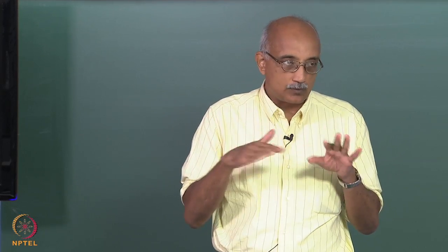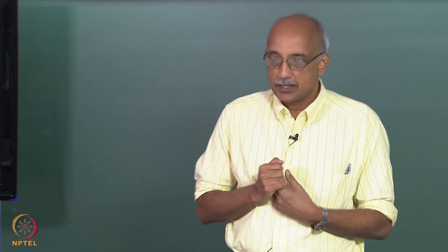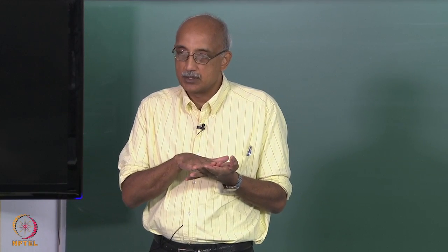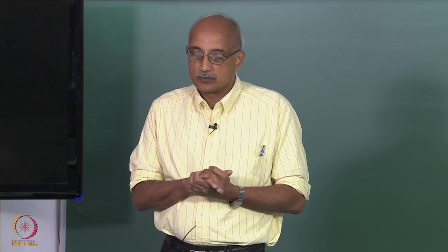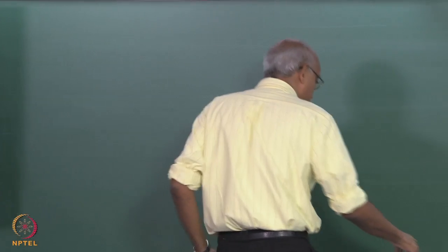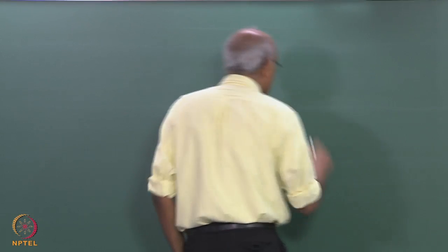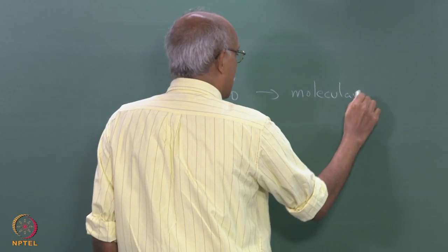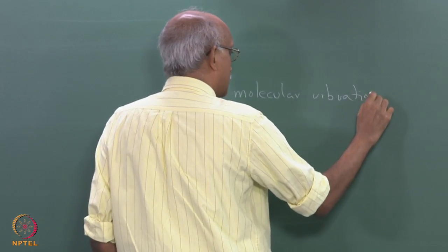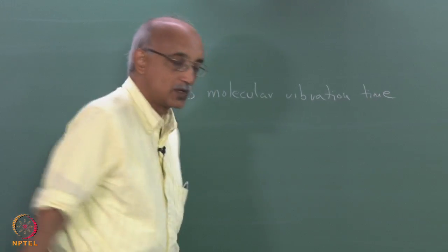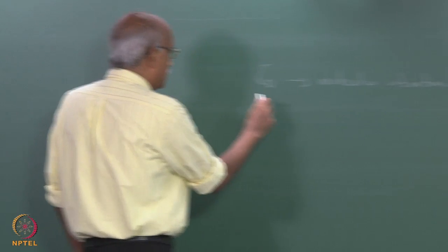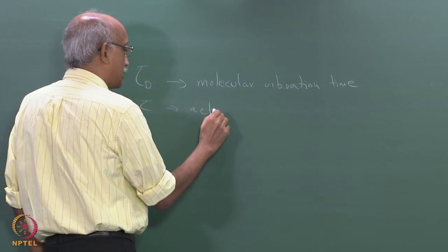Every molecule has its own vibrational mode, and in the free molecular transport regime, the molecule arrives at the substrate and sits there vibrating for some period of time, and then it leaves. So, if you call that time some tau 0, this is the molecular vibration time on the substrate, a characteristic time for which the molecule sits and vibrates on the surface, then the actual residence time